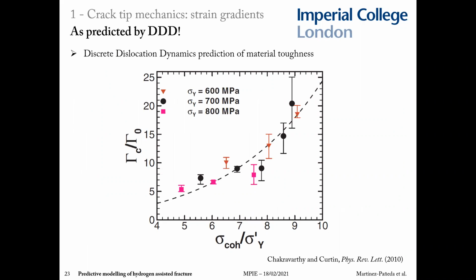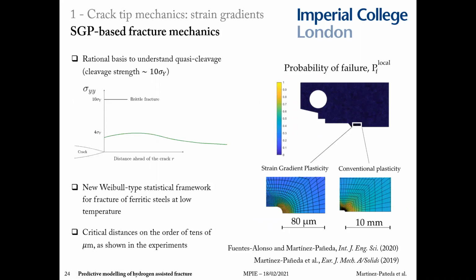You can see, this is from Bill Curtin's group, that fracture is attained at critical cohesive strengths that are up to 9 times larger than the yield stress. So this is much higher than the maximum stress levels that you predict with conventional plasticity models. And this stress elevation has allowed us to not only bring some insight to the hydrogen embrittlement problem, but also to rationalize many brittle processes that occur in the presence of plasticity.